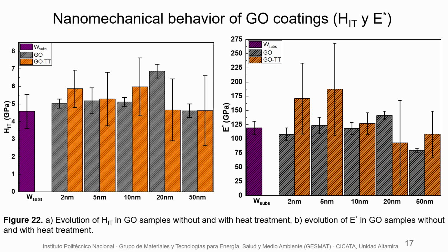Also, in the reduced elastic modulus, we show a slight increase from the non-thermally treated to the thermally treated samples, but the error bars are also very large. So we can conclude that the thermal treatment produced a diffusion of the copper to the surface, and this gives us this large dispersion in all the data presented.